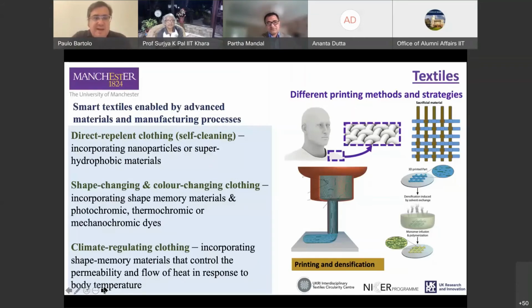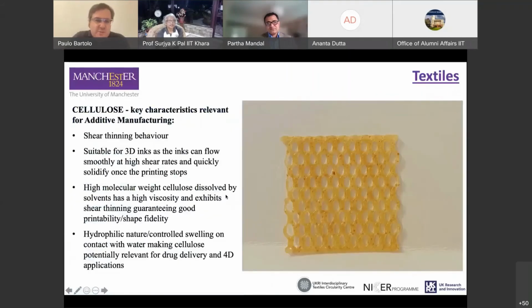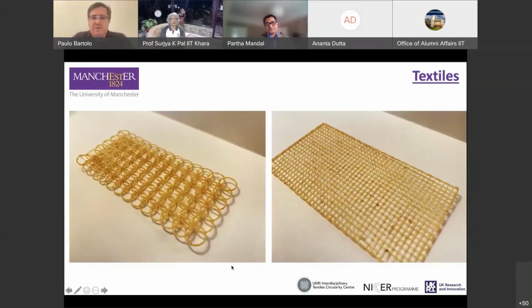We have done something regarding the first method, so mixing bacterial cellulose with degradable polymers. We used PLA. Despite the properties of both materials, and both of them are shear thinning, we observed some limitations in terms of the amount of bacterial cellulose that it was possible to incorporate. It was very difficult to reach values higher than 25-30% of bacterial cellulose. Because of that, the final structures are still very rigid, and we want to have something highly flexible. But this is an example of a structure. These are examples of other structures.